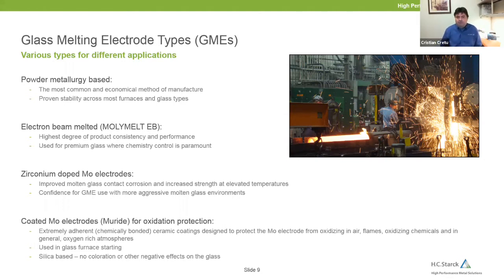It is definitely the most common. It's proven, everybody likes it. It's almost a commodity. It does have problems. As you can see, if you don't use the right type, you can end up with all kinds of bubbles or impurities. When you deal with powders, powders and voids go hand in hand. Minimization of voids in this process of powder metallurgy is critical, and we developed, with many years of experience, a variety of methods to minimize these, which we believe sets our GMEs apart and gives them additional value.